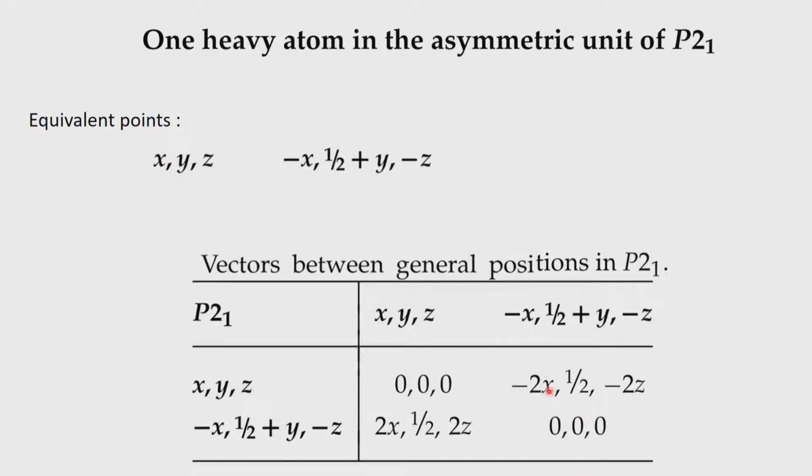So, in a space group like P21, y can be anywhere, y is arbitrary because it is along a two-fold axis. So, you can fix your y coordinate anywhere along the 2, 1 direction. So, 2x and 2z will solve for x and z. You easily identify now the Harker sections, which are this as well as that, corresponding to y equals half.